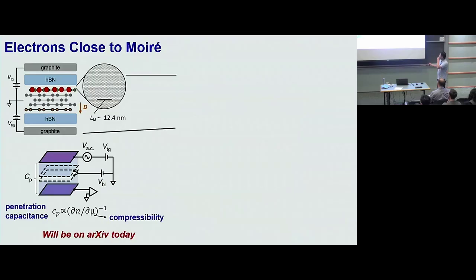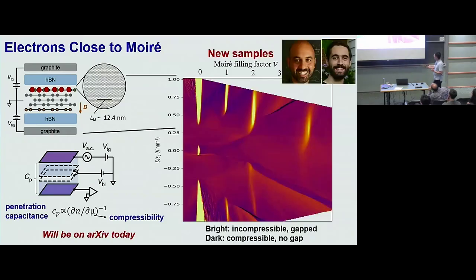So the first thing I want to show you is that, in addition to in-plane DC transport measurement, our colleague Ray is an expert at measuring capacitance, and that tells you the electronic compressibility. So we made a sample for him. It's a different sample from the transport device, right? So this one, you have good electrical contact when the electrons are pushed towards the Moiré. So your electrons feel strong Moiré potential. And you can measure compressibility, and you get a map like this.